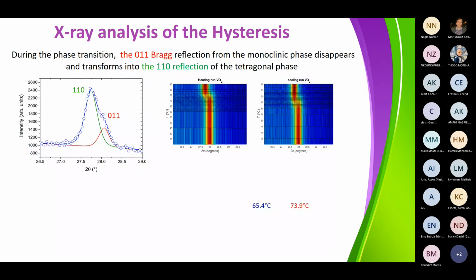So when you do that, typically this was measured, I cannot remember what the temperature was here, but it was intermediate. So you can see that at a certain stage, the system is passing from the rutile phase to the monoclinic phase. And at this specific temperature, there is a coexistence of the two phases. If you look at the shape of this reflection, it cannot be described by only one line shape.